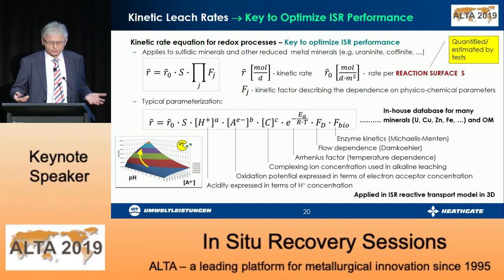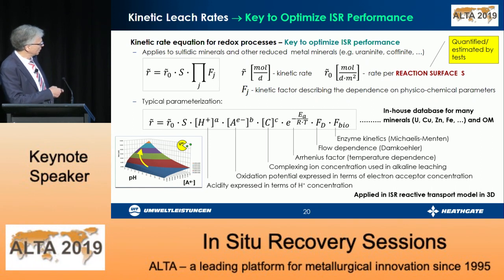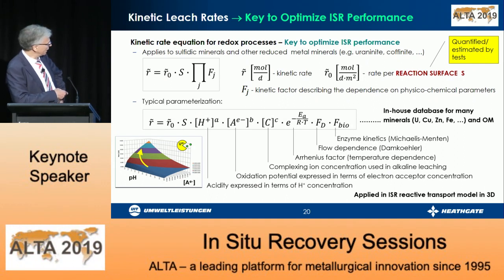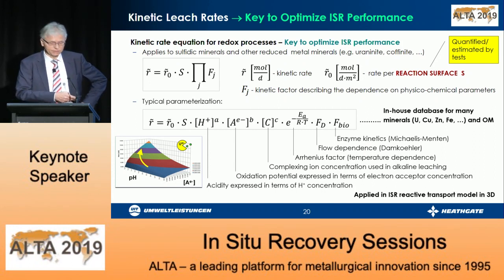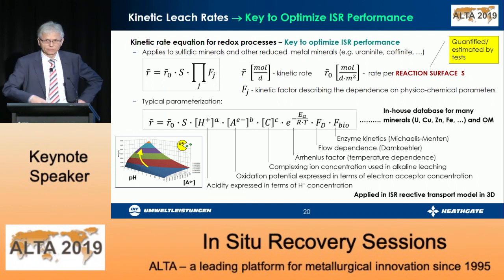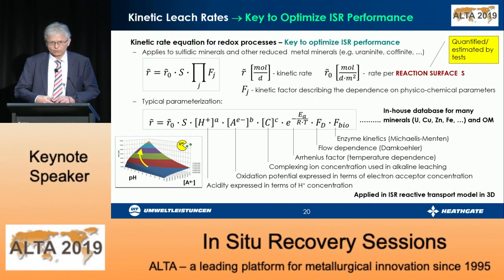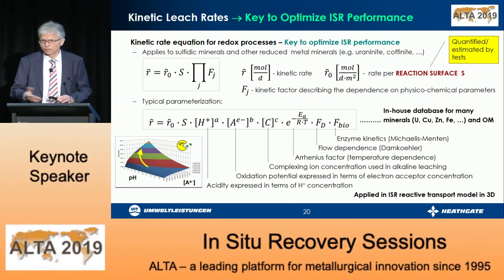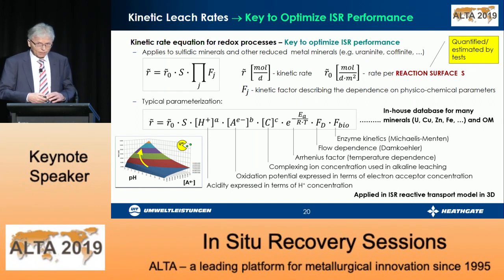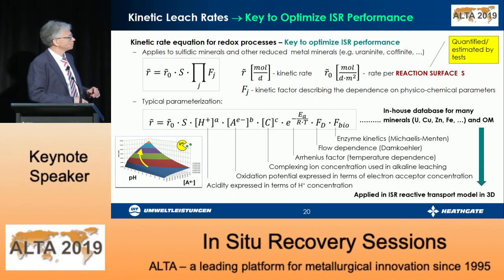Just to emphasize the importance of understanding the kinetics in dependence on such critical parameters, I show here a little figure that is the kinetic rate of uraninite leaching as a function of the pH value. The lower the pH, the higher the rate. And on the one side, and this is the electron acceptor concentration, of course, the more oxidant potential you inject, the higher the leaching rate. The same has been studied for all the competing interfering reactions, including pyrite dissolution and also the degradation of organic matter in the underground. And this was the key for solving what we call the redox puzzle.